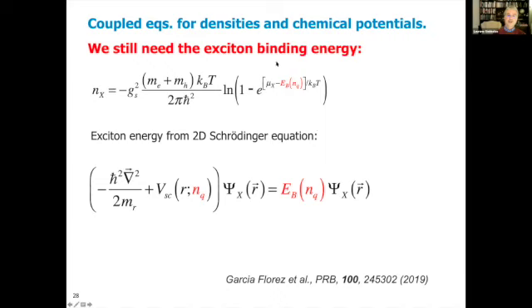But we still, in these equations, need the exciton binding energy. That is not the 193 millielectron volt that I talked about earlier, because that was for a single exciton. And if you have many excitons close together, and in addition, if you have free charges, they start screening the Coulomb potential. So the exciton binding energy will depend on the density of photoexcitations, which determines the density of free charges. So the two-dimensional Schrödinger equation now contains the kinetic energy of the electrons and the holes, plus a potential energy that is a screened Coulomb potential with a screening length depending on the density of charges. And that gives you the exciton binding energy as a function of the density of charges.